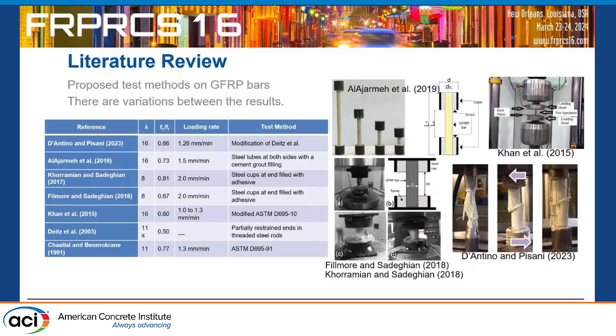But other people like Khan tried to use just bare FRP, like ASTM for all FRP composites, and we are going to show that one underpredicts hugely. And previously, my previous PhD student, Khorramian, and my other student, Brandon Fillmore, tried to have a cap at the top and keep the aspect ratio, free length over diameter, of 2, and we got good results. But again, there was always some localized compression, I believe kind of premature failure in the cap area. So with the new fixture, we think that we are solving the majority of it.